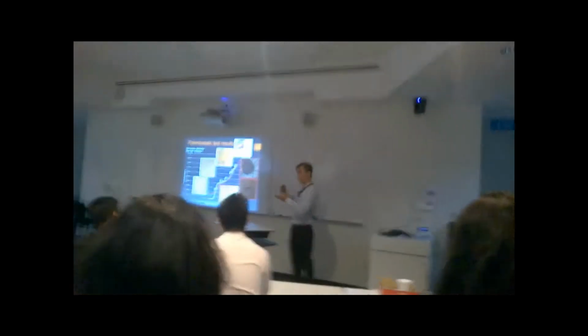Therefore, we only have the microstructure before and after the test. So in order to see the whole process of the microstructure change along the analytic curve, I decided to do the potentiostatic test. The difference between the potentiostatic test and the polarization test is that the potential of the sample doesn't change; it keeps a constant value for the whole test. So at the end of the test, I can remove the sample and examine the microstructure at that particular potential. It's showing me that on the graph here.